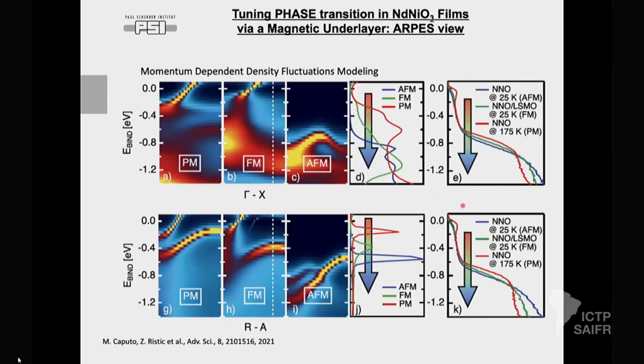In order to also model the system, we use the same momentum-dependent density fluctuation modeling. What we could see here is that in the paramagnetic state you can see this band here. In the ferromagnetic state there is a bit of redistribution of the spectral weight, while the antiferromagnetic state will open a gap. Here I will ask you to pay attention to this cut. There are more or less similar things: here there is a bit of shifting of the band down, while in the antiferromagnetic case a gap opens.